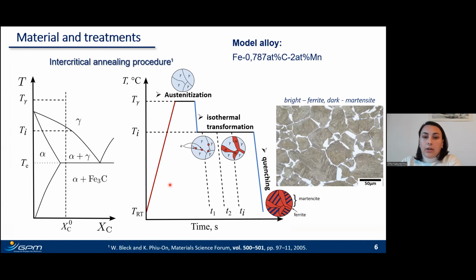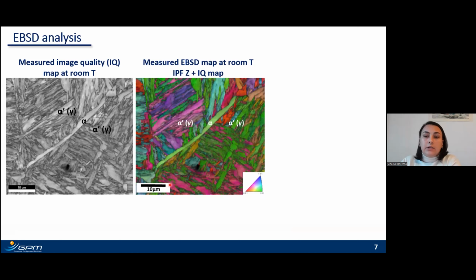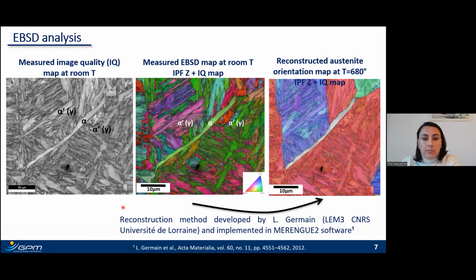Then to localize a certain alpha-gamma interface and to obtain the crystallography information, the EBSD technique was used in this work. But we have to keep in mind that at room temperature, we are dealing with a martensite-ferrite microstructure instead of austenite-ferrite. And since in low carbon steel it's very hard to distinguish BCT martensite from BCC ferrite, the image quality map, which you can see on the slide, can be used to provide better visualization of the martensite-ferrite microstructure. In any case, it's possible to use the EBSD map measured at room temperature to reproduce the original EBSD map at high temperature, using the reconstruction method developed by Germain and implemented in MERENGUE2 software.